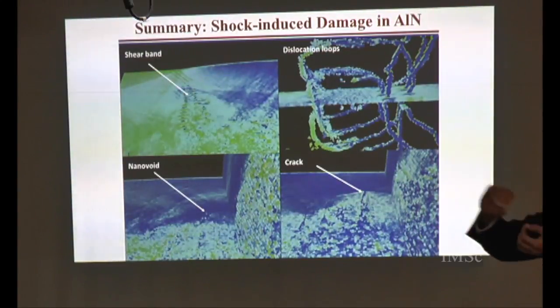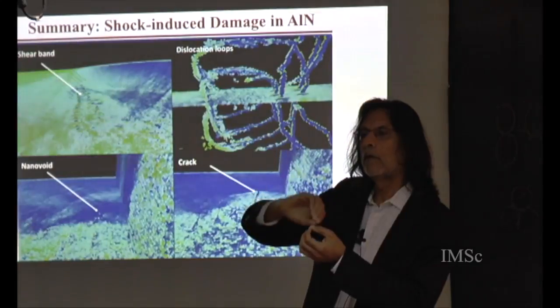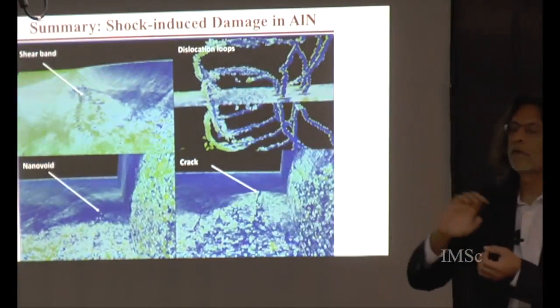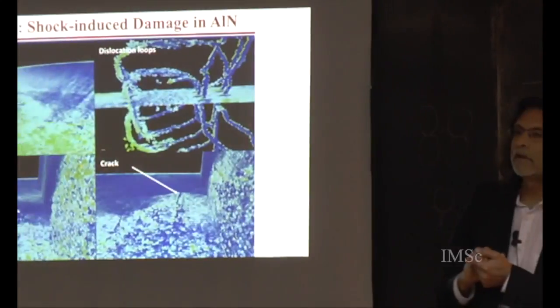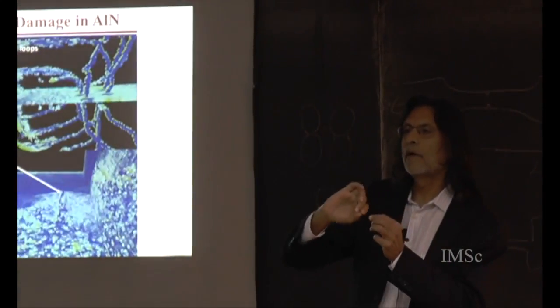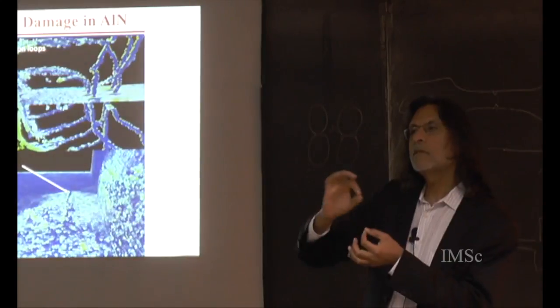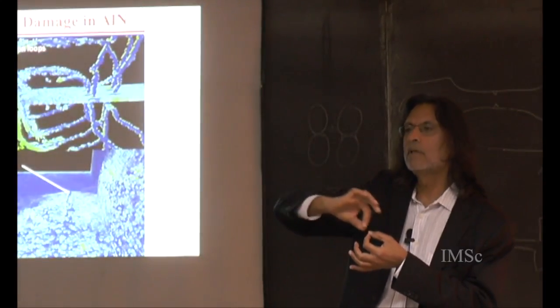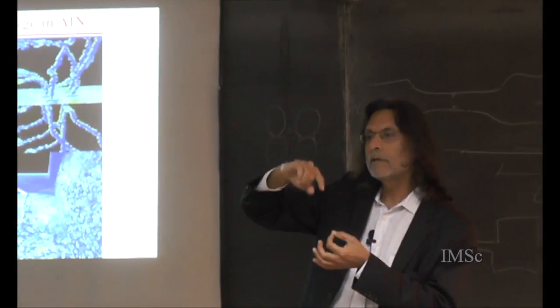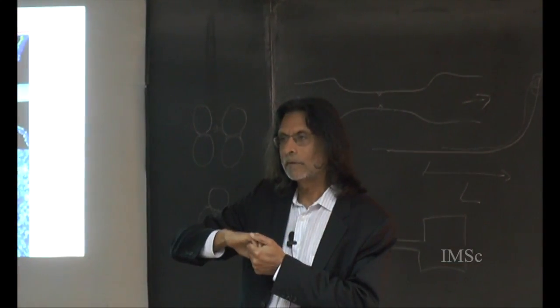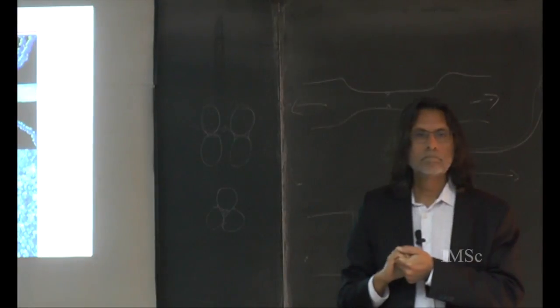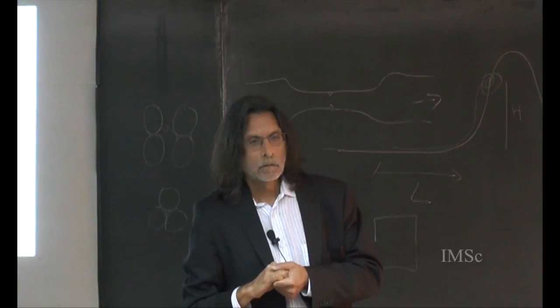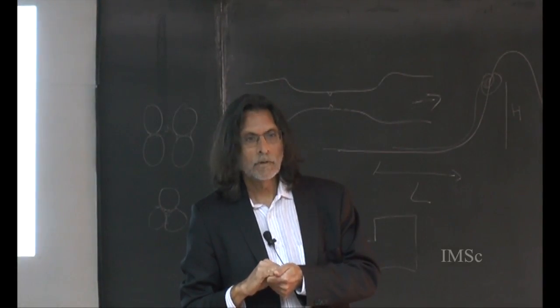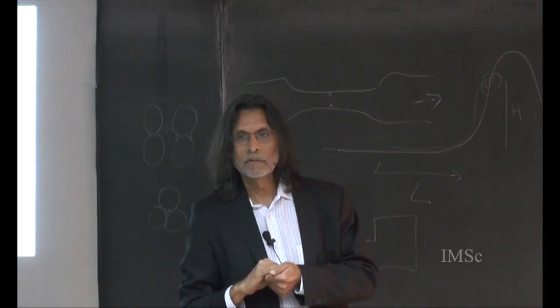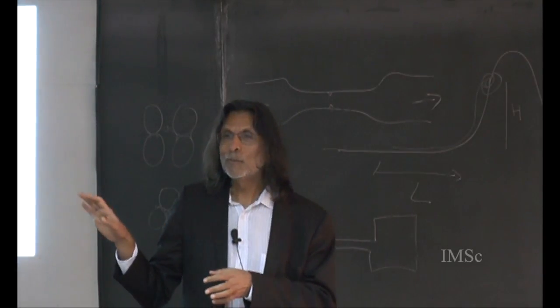So, in this system, atoms which are not 6-fold coordinated, from there we do the analysis to find what the dislocations are. In this system, the dislocations are not running straight like you see in crystals, okay? These defects are in the form of loops, okay? It's analyzed in terms of Burgers vectors. Right. So you need a lattice. Right. Absolutely. So any other question before I move to the next part?